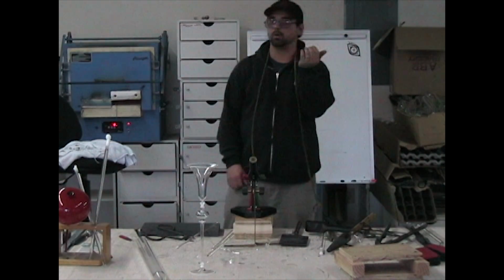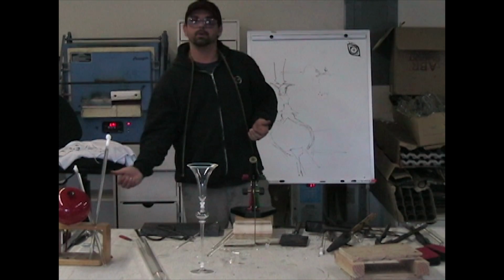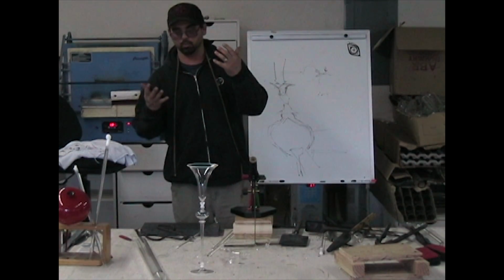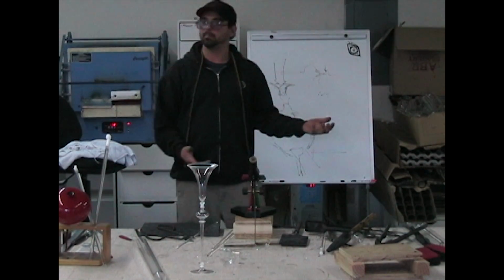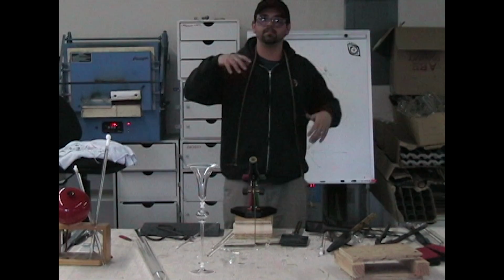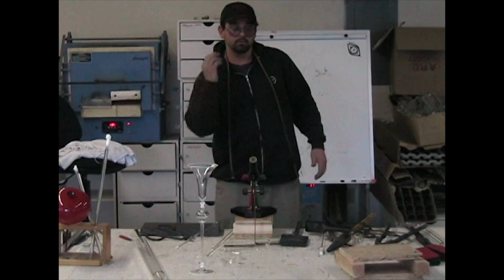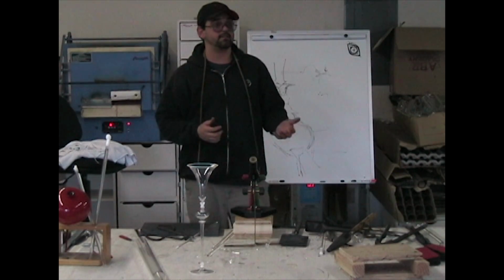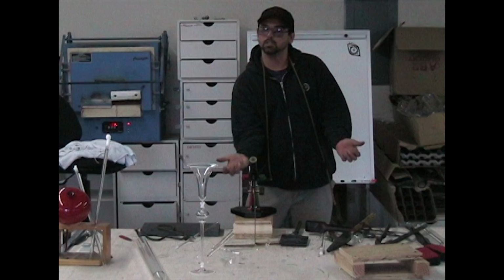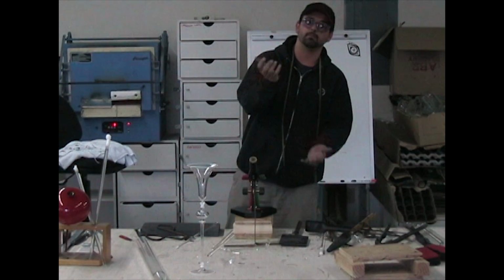Because it's always a lifting motion. I know some people with the soft glass bench do a downward motion with it, but gosh, there you're working with gravity to destroy your piece. By lifting, you're balancing out gravity. You always spin at the rate that the glass wants to fall, which sometimes means not very fast at all. Just slow, even rotations. But then with the jacks, it's a lifting motion as the glass wants to fall. So it balances out.